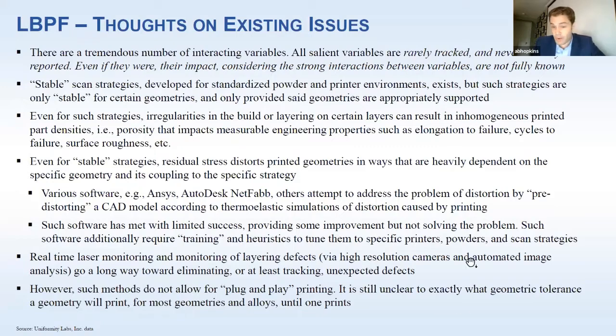Monitoring of the laser: you have fluctuations in the power delivered to your printers. Your laser might suddenly drop from 100% to 90% power. Again, the newest printers are monitoring the laser in real time every layer, so you can track that. You can learn, oops, we're at 90% power for 100 layers. We may have defects unless we designed a scan strategy that was robust enough to function at 90% power as well as 100%. This solves most of the problems that exist commercially, but it's not widely deployed yet, and it doesn't solve all the problems. And once again, if you're going to put this part on an aircraft or in the human body, particularly in an aircraft, you really need to solve all the problems.